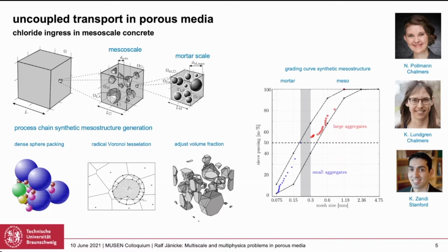chloride diffusion here. So at that time, we didn't have access to fancy 3D imaging equipment, so we were doing our 3D analysis on synthetic microstructures. Just to give you an idea how to produce such a microstructure consisting of aggregates with a certain grading curve or size distribution: typically we start with dense sphere packing with a predefined relation of the radii of the spheres. This is used for a Voronoi tessellation or radical Voronoi tessellation, and from that we can then adjust the volume fractions, getting such aggregates. And actually, we can design the structures in a way that they really lie between some bounds, design codes, whatever. Those ones we took from literature, for example.